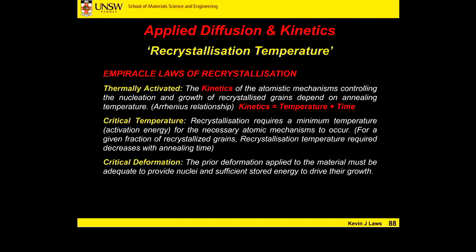There's also a critical deformation. The prior deformation applied to the material must be adequate to provide nuclei, remember this is still a nucleation-based process, and sufficient stored energy to drive their growth. So if you apply a small degree of deformation to your material, in terms of our stress-strain curve, if you move up only to this point, just starting to plastically deform, there's probably not enough deformation or stored energy in the material to nucleate regions for recrystallization to occur, or enough energy stored in the structure to drive recrystallization.